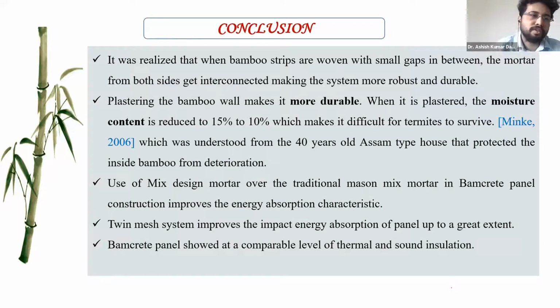And this is the conclusion that I want to highlight here. It was realized that bamboo strips are woven with small gaps in between for the mortar. Both sides get interconnected, making the system more robust and durable. Plastering the bamboo wall makes it more durable. With the plaster, the moisture content gets reduced to a very significant level, which makes it difficult for termites to survive.